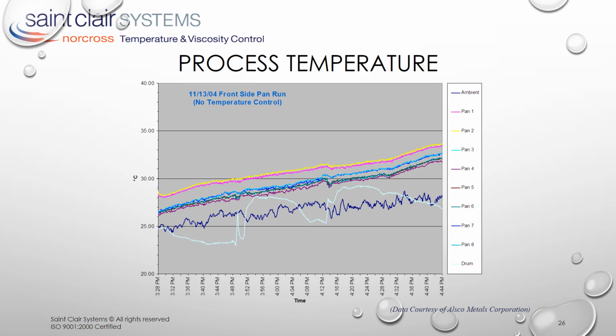Plotted here are ambient temperature, drum temperature, and the temperature at 8 points across the width of the roll. This graph reveals many interesting details about the roll coating process. The first thing that catches our eye is the increase in coating temperature from 26 to 32 C over the course of this hour. This represents head-to-tail variation. Remember back on slide 2 when Valspar told us our window of operation is just 3 degrees C? Here we have nearly doubled it. It's also important to note that ambient rises just over 3 degrees C over this same period. The difference between the ambient increase and the process increase is the result of the friction we just described. This friction-generated heat explains why controlling the ambient temperature in the booth cannot accurately control the temperature of the coating.